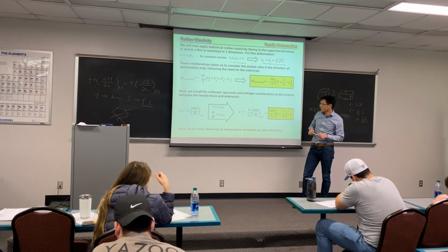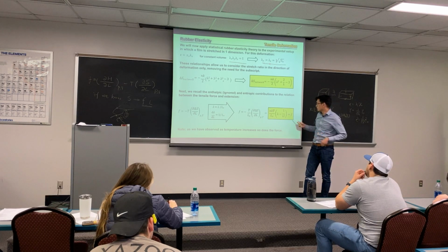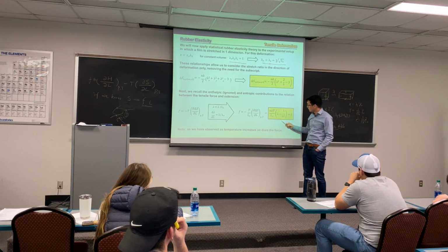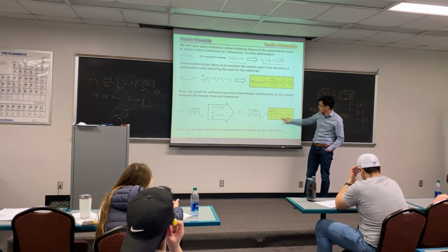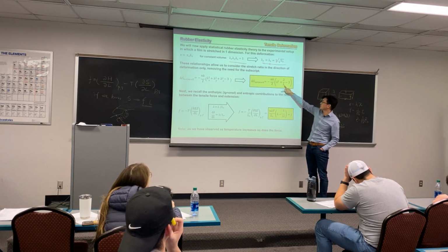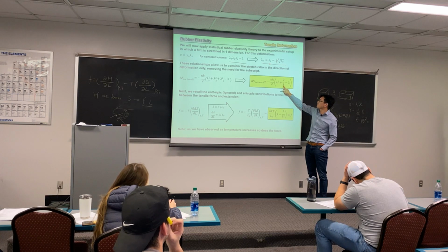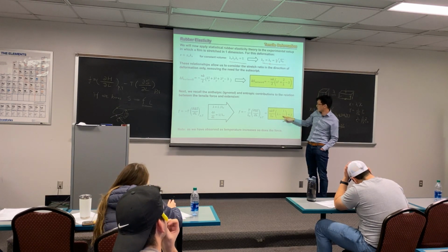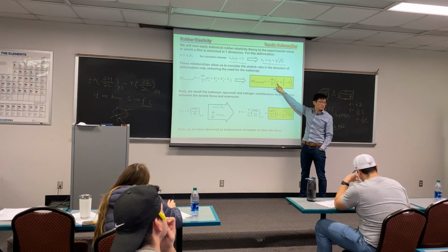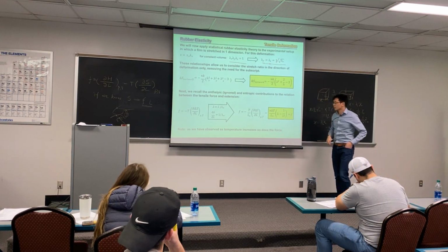Pay attention that it's not as linear as we would expect from Hooke's law. Hooke's law tells you your force will be spring constant multiplied by draw ratio, but it's not, right? There's a second term that comes into play, which is lambda square. Everybody knows if you take a partial derivative over here, it will become this. The constant will drop out. Lambda minus 1 will be equal to minus lambda square. Lambda square will become 2 lambda if you take a derivative of that. And the 2 cancels out with this 2 and this 2. So that's how we get the force.